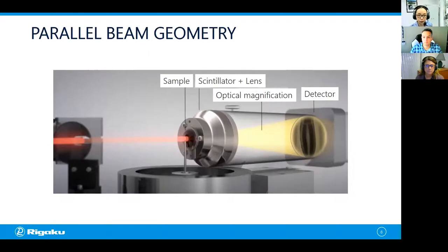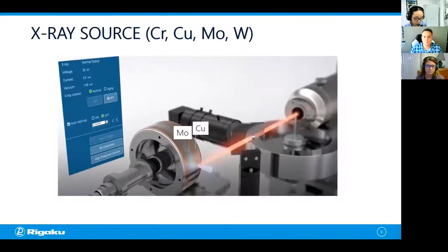Now on the X-ray source side, the particular system we're using today is called the Nano3DX. And the Nano3DX uses a rotating anode X-ray generator. This is a high power microfocus X-ray generator. And inside of the X-ray generator, we have this copper target. I will show you an actual one in a second. And if you have the electron beam hitting this copper cup, you will have copper characteristic radiation, which is about 8 keV, and it is pseudo-monochromatic, and that goes to the sample. If you want to change the X-ray energy, let's say to 17 keV, which is a characteristic radiation from molybdenum, then the electron beam stays here, but you shift this anode a little bit so that the electron beam hits molybdenum. And this switch can be done just by clicking a button on the computer screen.